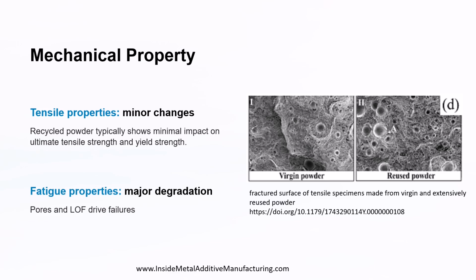Recycled powder increases pore size, raises the likelihood of lack of fusion defects, and introduces greater scatter in fatigue life. For components used in aerospace, medical implants, or any application involving cyclic loading, even small increases in defect populations can compromise safety margins. That's why high reuse ratios must be approached with caution in fatigue-critical environments.